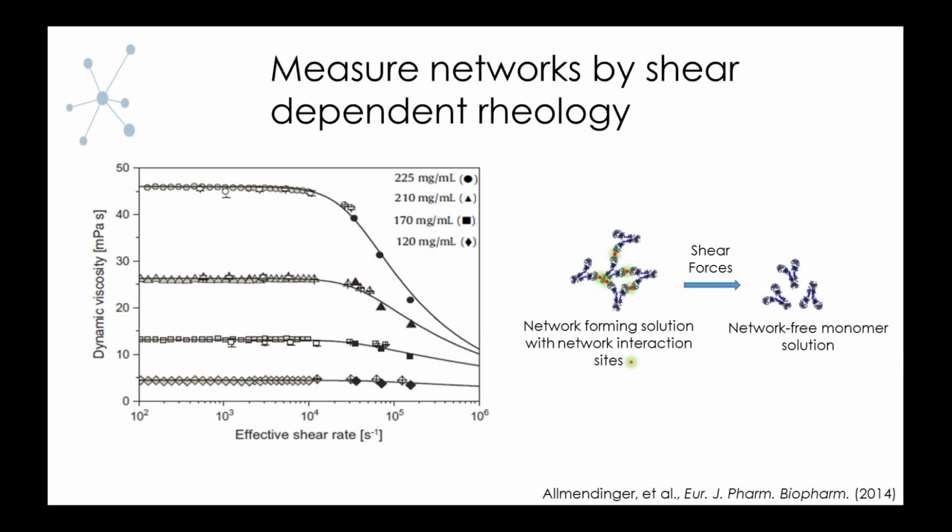So okay, now that we've established what we think is happening, we want to see what physically, by screening these interactions, is changing in the solution to reduce the viscosities. So our theory was about MAB oligomers and networks. We believe that if you have a networked solution, something that looks like this, where the proteins are all interacting with each other, if you shear the solution hard enough, you can add enough force to break these networks apart back into a free monomer solution.